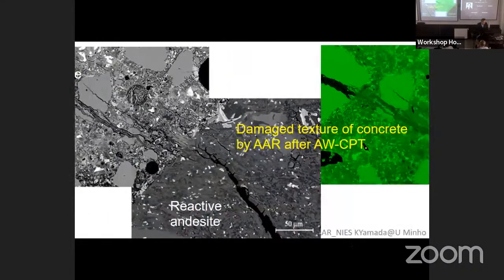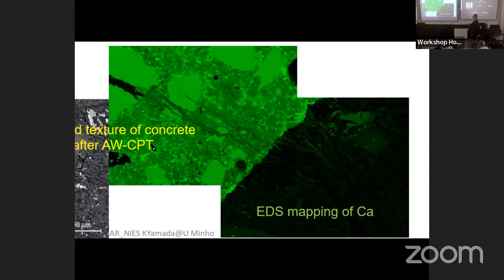And this is an EDS mapping of calcium. Of course, alkali silica gel is sodium silicate in its original state. So there is no calcium in the crack in the aggregate. But passing through the cement paste, you can see some amount of calcium. But there is no calcium again. From this texture, what do you think? What can you imagine? There is some basic knowledge. Silica gel must come from the aggregate because there is no other source of silica gel.